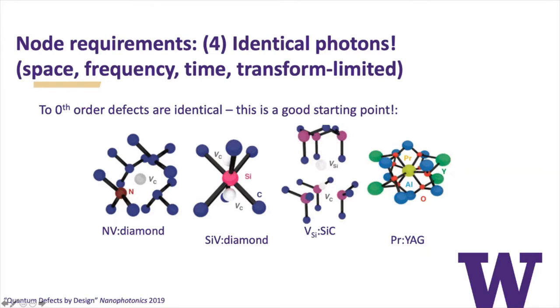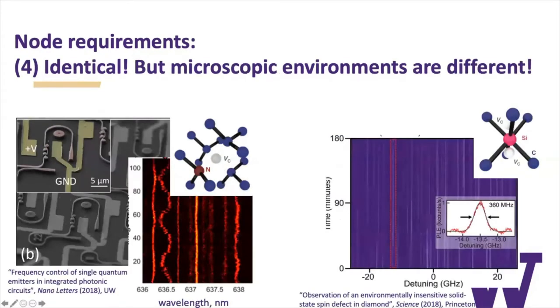So to zeroth order, everything's identical. That's a good starting point. But even if the actual NV center is identical, you can imagine just a few lattice sites away, there can be another defect. And that defect, because it can be so close to this NV center, can cause the microscopic environment to be slightly different. And so the energy is slightly different.